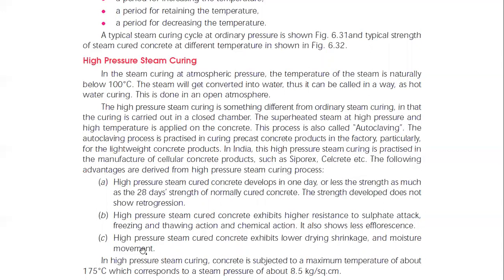So basically, some are the basic advantages of high pressure steam curing, in which the first one is that the 28 days strength of concrete is gained in less than 1 day. The second one is that high pressure steam curing also gives resistance to sulfate attack, freezing and thawing action. Also, high pressure steam curing exhibits lower drying shrinkage and moisture movement. So it also controls the moisture movement and shrinkage phenomena.